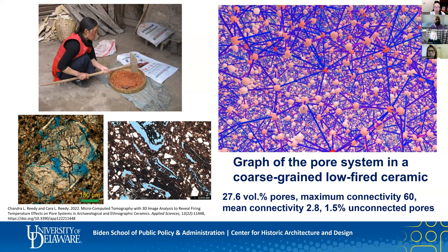And this creates many locations where intragranular pores are in contact with each other and with some adjacent intergranular pores in common, raising the overall connectivity values. There are a lot of pores here. Most of them are connected to at least three other pores, and some to a lot more than that. And only a very few are isolated pores.